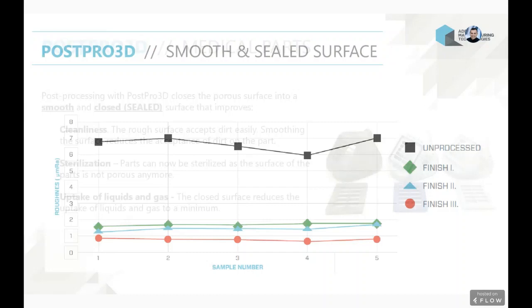And the reason why there is a lot of variability on the density sometimes is because there are different amounts of residual powder that gets adhered to the surface of those parts. So your surface roughness and your density values are going to be fluctuating a lot based on how many parts you nest and how well you are controlling the thermal conditions of your process.